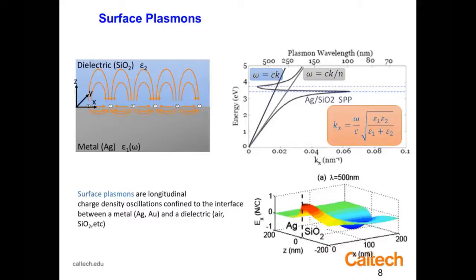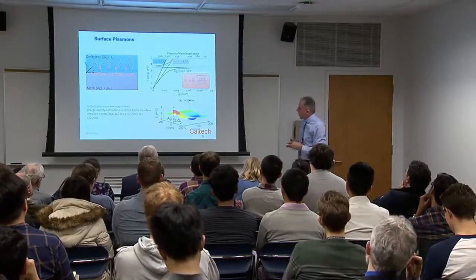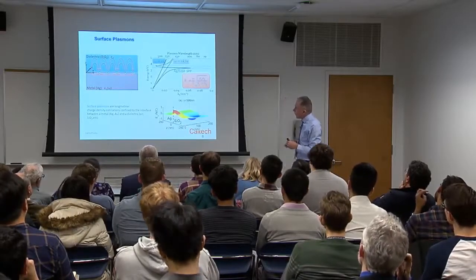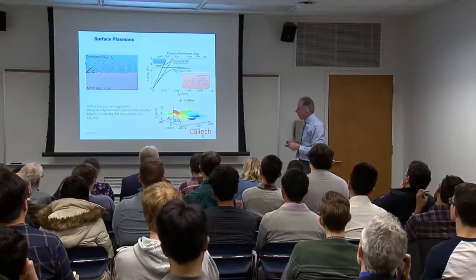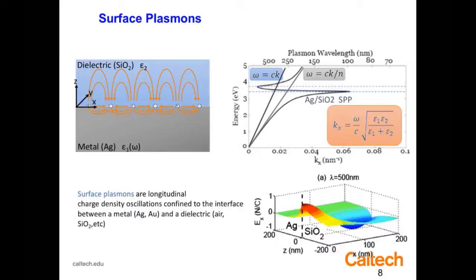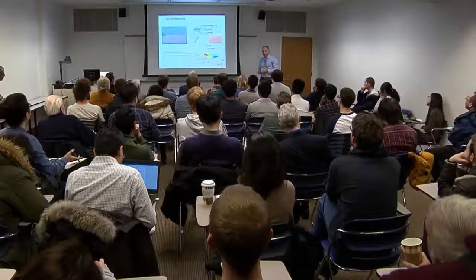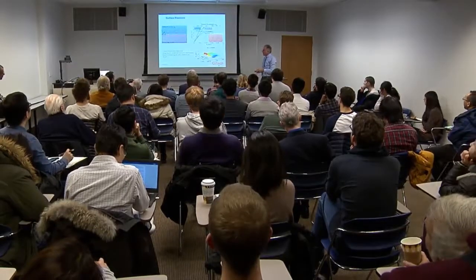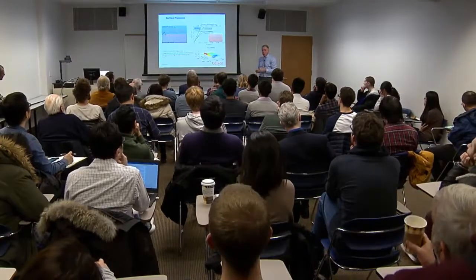Now you also see that this curve bends back, and it goes through a susceptibility resonance. And there's a very strange mode here. I won't get into this today, but this is the range where strange things happen, like negative index and other material properties. But that's a story for another day. The net result is that at a single interface between a dielectric and a metal, we can make a surface wave that propagates. It propagates very much like a surface wave propagates on the surface of the water.